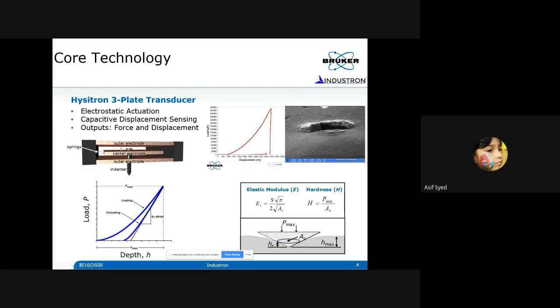Now, if you know the physics of it, you can see that these are like parallel plate capacitors, and the center plate can move in between these two outer plates, which means that the capacitance can change. And if you have a way of measuring the change in capacitance, you can measure the displacement of the central electrode. So this transducer can be used to apply force as well as measure displacement. So it's a very compact, very simple actuator and sensor.